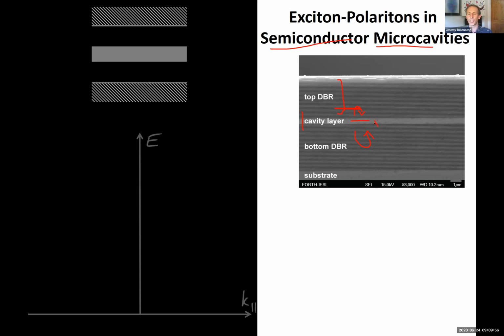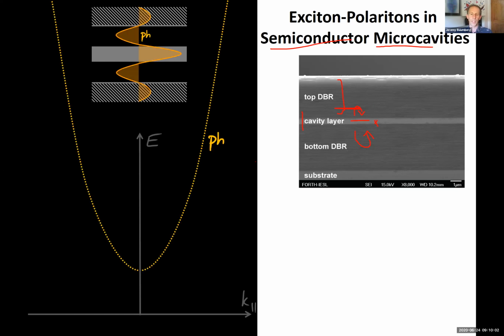So we have excitons that are sitting inside these quantum wells inside the cavity, and we have photons going around the cavity. If I draw the dispersion relation, which essentially means if I come in with light from some particular angle, then it has some in-plane component here, K parallel. So I get this parabolic shape here. That's because the condition for constructive interference for the cavity mode means that I have to have a particular K perpendicular. So if I come in at higher angles, I need to have a higher frequency. So I need to have a bluer photon to come in. So this is basically the cavity photon mode, which is trapped inside that cavity.